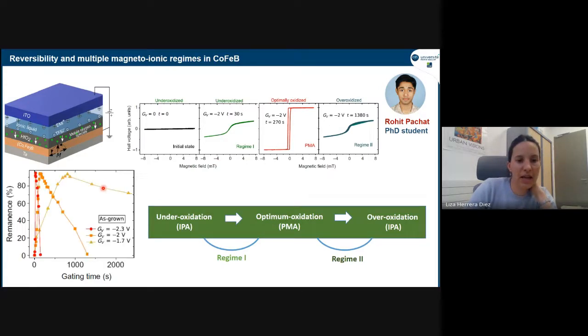Now, what is interesting is that this is the remanence as a function of the gating time. You can see the remanence going up from this state to this state. There's the first ramp up, and then it ramps back down. When it goes in this direction, you can see that it shoots up quite a bit, and then the second line has another slope. So we could probably tell from this that the processes are not the same. This to this is not the same as this to something else. This is what we wanted to probe here, and so we called the under-oxidation to PMA regime 1, and then PMA to in-plane, because of over-oxidation, regime 2.